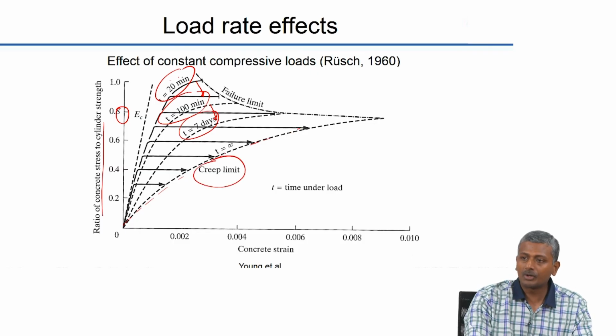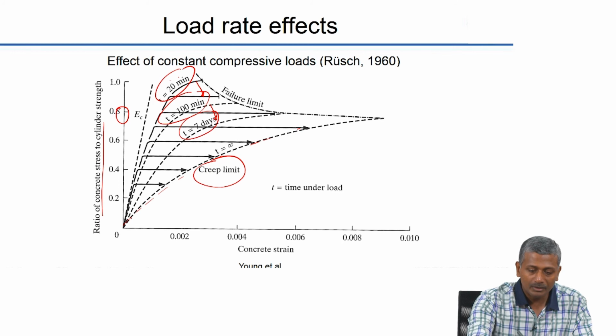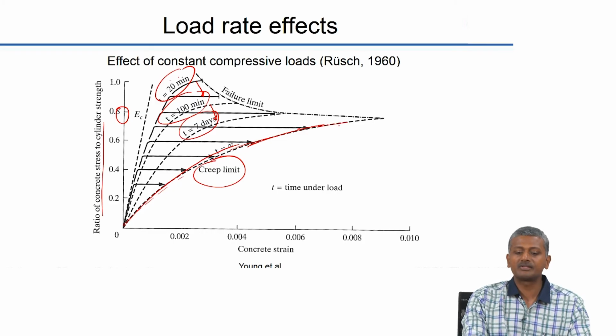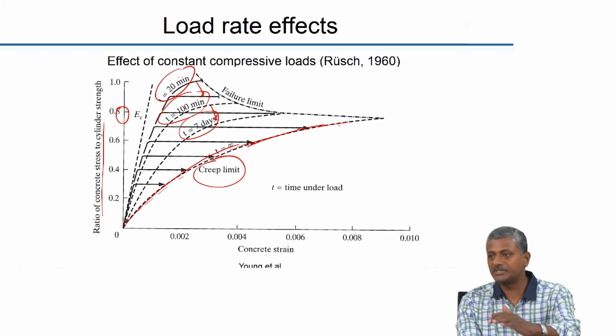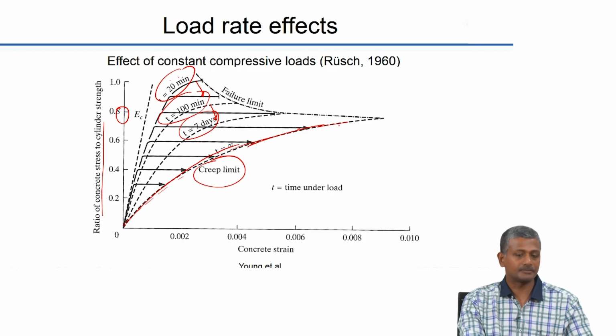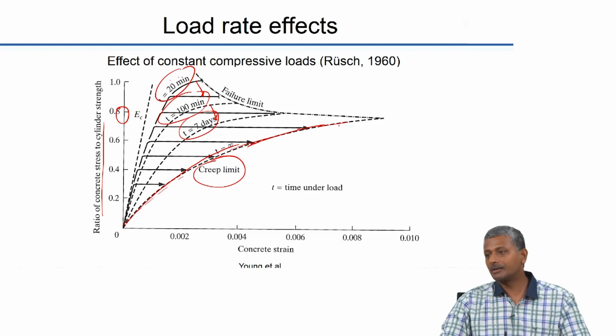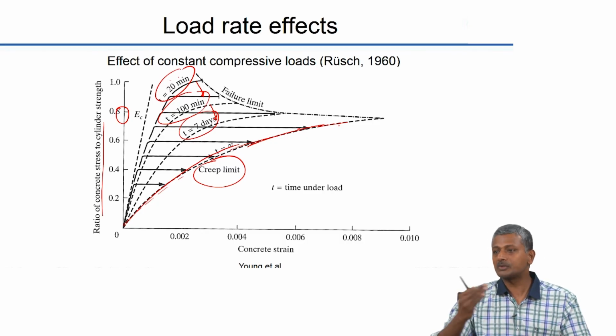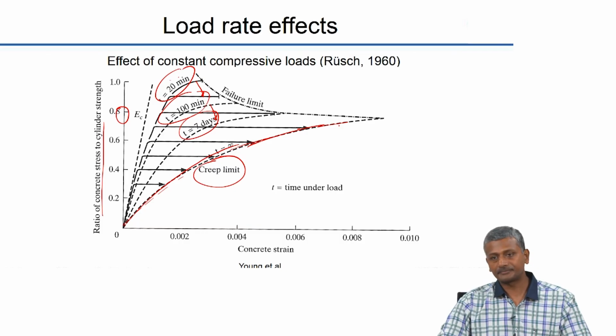When you are applying your loading over infinite time, your stress to strength ratio as a function of your concrete strain will go as per that curve described by the creep limit. So, the greater the amount of time that your system is under load, the lesser it can perform with respect to its ultimate compressive strength.